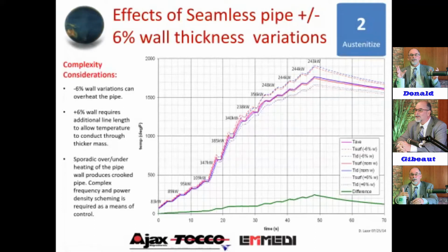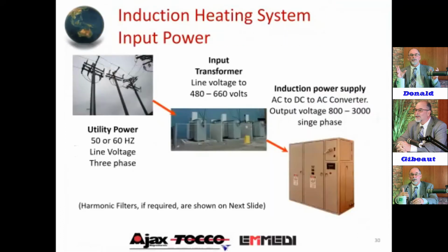So we can run seamless tubing. We have to lower this power density in the front end to do it, and that reduces the line speeds typically, but there's scheming we can do with a little bit longer line. So we can and do and have, and most of our lines run parallel seamless tubing as well as ERW.